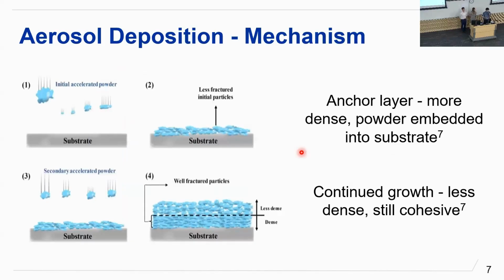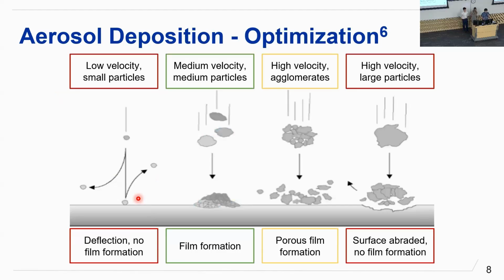So with that, as the particle is accelerated at the substrate, it will hit and make this anchor layer by fracturing the moment it hits the substrate. Through this, it creates this anchor layer that's very dense and cohesive. And then as continual deposition occurs, it slowly creates a less dense layer, but it is still very cohesive. And what we want to see is right here, this green, where we have a medium velocity or medium particles. As the particles are accelerated towards the substrate, they hit, fracture, and densify on top of itself.